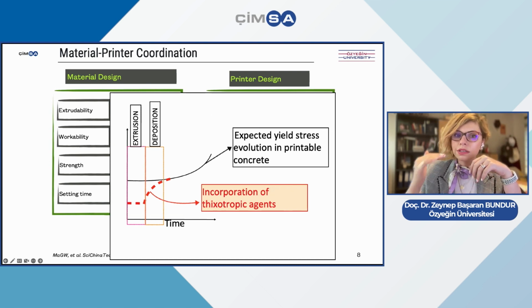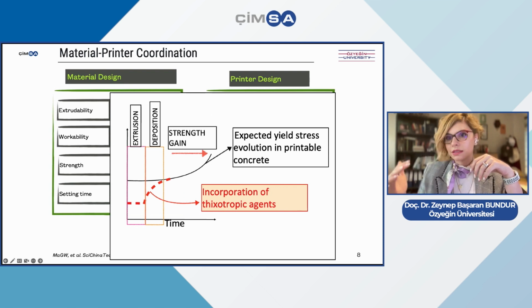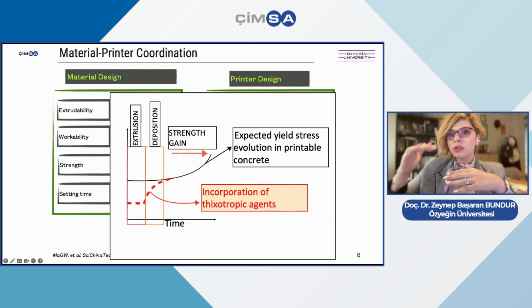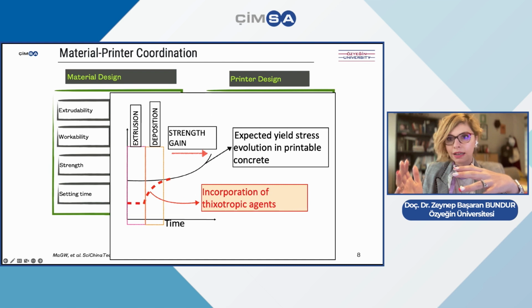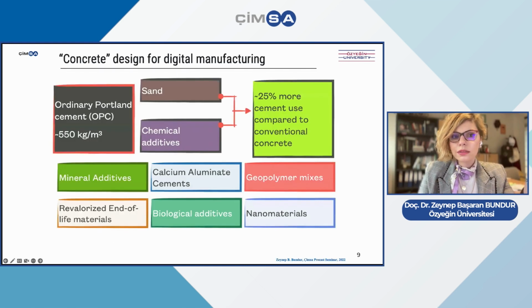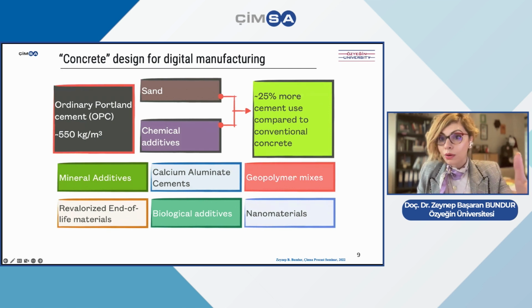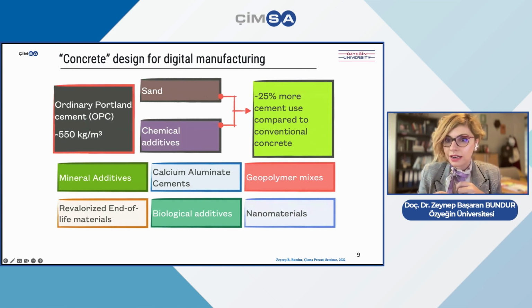That's where the chemicals come into effect, basically. So after the printing, we need to have a yield stress evolution in the printable concrete. And that's where we need incorporation of thixotropic agents and properties. And we have different approaches in that sense. Here, we can have ordinary Portland cement, and we can have mineral additives and calcium aluminate cements as well.